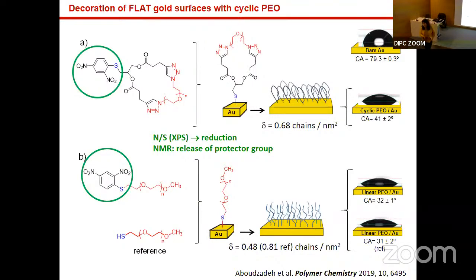Okay, and we measured the contact angle of these gold surfaces modified with the cyclic polymer and the linear polymer, and we observed a decrease of the contact angles, meaning that the gold became more hydrophilic. That's good, but we also observed differences in the cyclic brushes in comparison with the linear polymers. The value here was about 10 degrees higher than the linear one, meaning that this is more hydrophobic than the linear one. So we can modify surfaces with the cyclic polymers and make them more hydrophilic or more hydrophobic, depending on the modification.